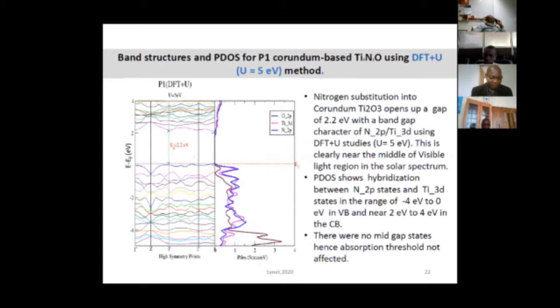So in the band structure of P1, we can actually see that we are having strong hybridization between nitrogen 2p and titanium 3d orbitals within the range of -4 to 0 eV in the valence band, and 4 eV in the conduction band. So there were no mid-gap states. That was something good to notice when we checked on these oxynitrides.